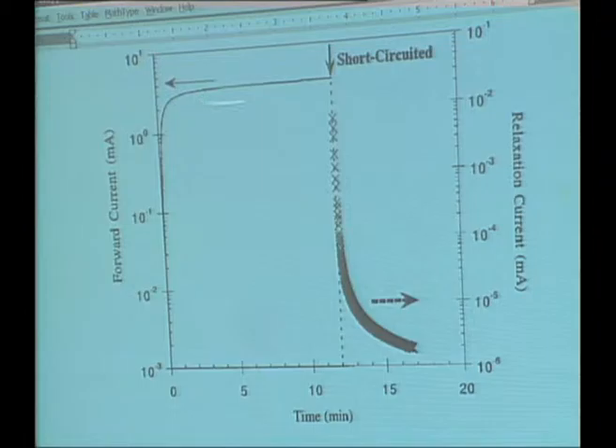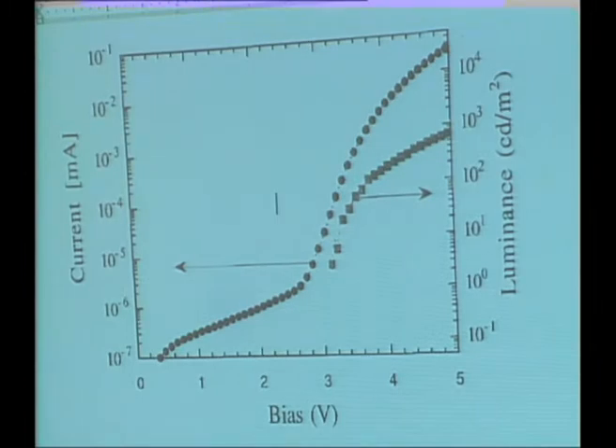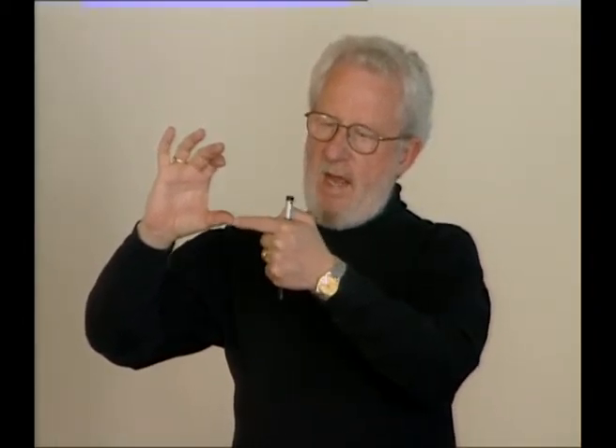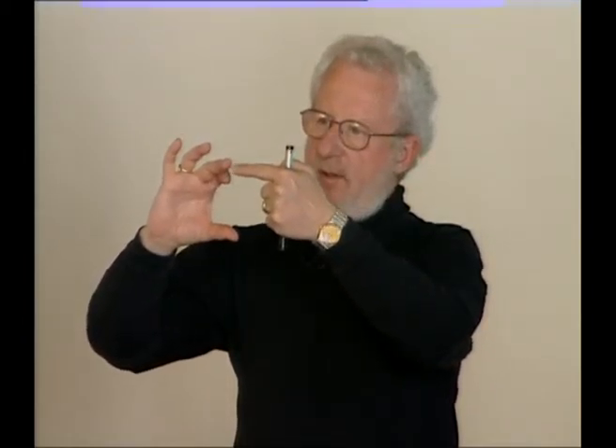So we doped the polymer, we made a battery, we discharged the battery. While the battery was charged, electrons and holes are flowing inside, and you get light out. So one can get pretty good brightness. And the nice thing with this concept is that the injection is insensitive to the electrodes that you use. I emphasize that when you make LEDs, you really have to be careful to match the anode with the top of the pi band and the cathode with the top of the pi star band. And if, for example, you want to make red, green, and blue pixels, then you might have to think about using different contacts, different metals for contacts, and that's terrible. Here, the contact is self-made. That is to say, the doping itself gives you an ohmic contact, and it's all finished.